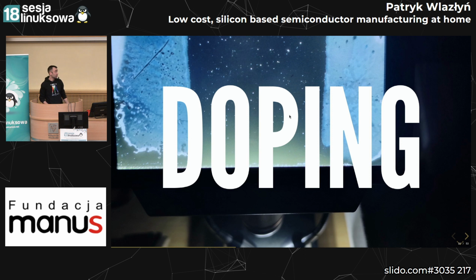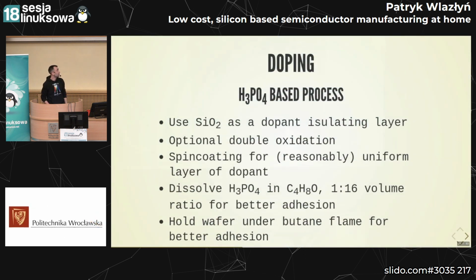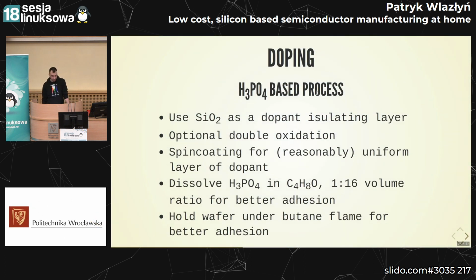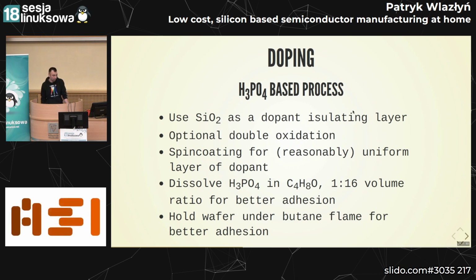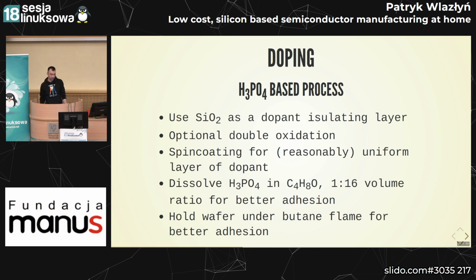So pretty simple stuff. And now it goes into doping, so introducing impurities like phosphorus and boron into the silicon. This is an example process for a phosphoric acid-based chemical process. You use silicon dioxide as a dopant isolating layer. If you don't want to dope certain regions, you just grow a thick enough oxide that it will stop any doping. You do an optional double oxidation, which is a process I will describe if we have some time left at the end, but for now let's leave it at that.